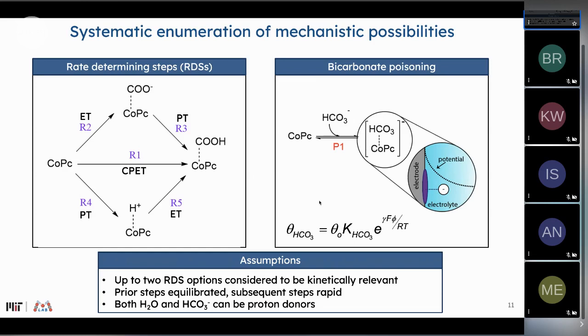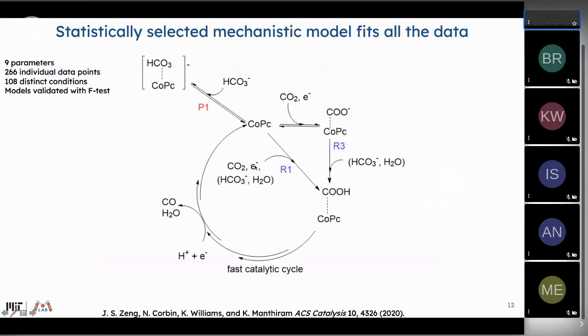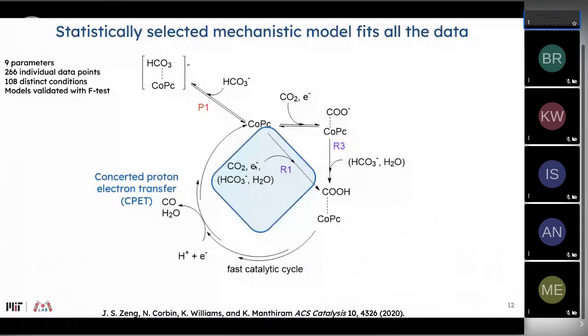So we can take this and enumerate the steps. We allow in our mathematical formulation for there to be up to 2 RDS options in the kinetically relevant steps. All other steps are equilibrated. And we also allow for both water and bicarbonate to be proton donors. In this system, we have collected 266 individual data points at 108 distinct conditions. We implement the models that we showed on the previous slide, and we validate them using what's known as the F-test, which allows us to quantify the goodness of fit.